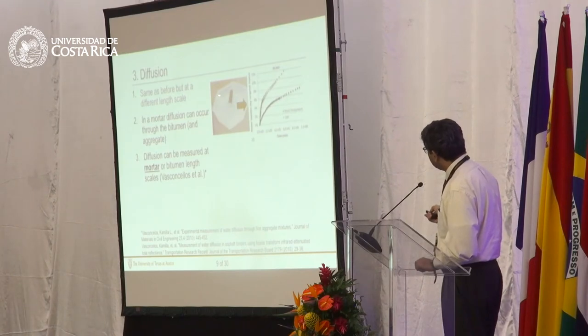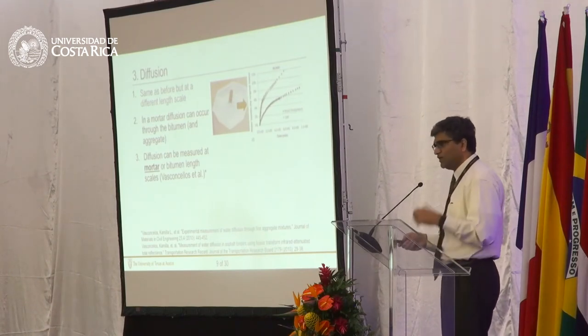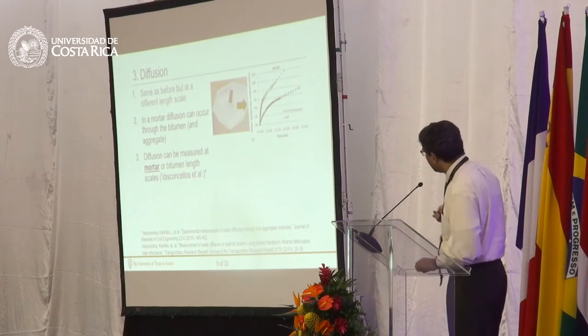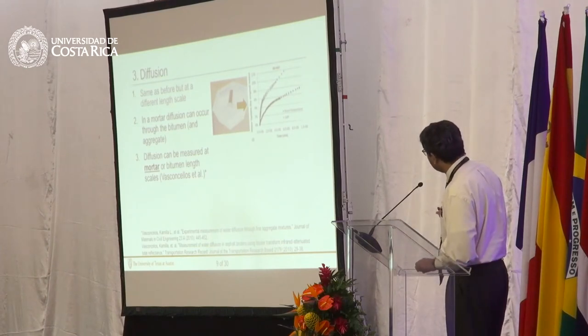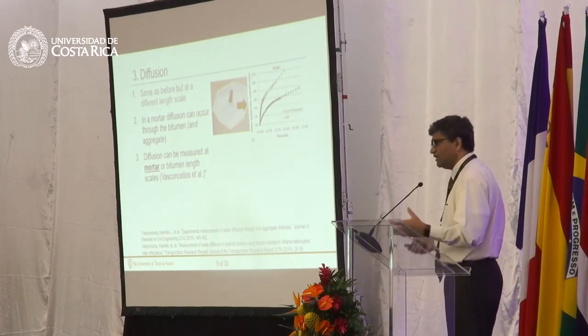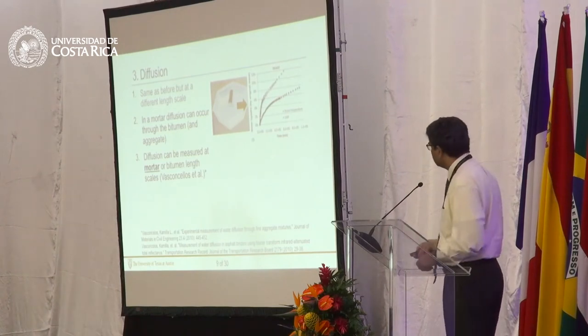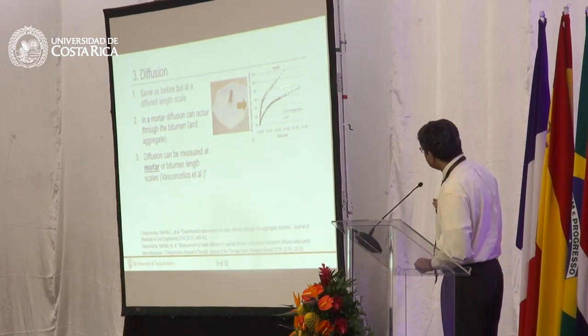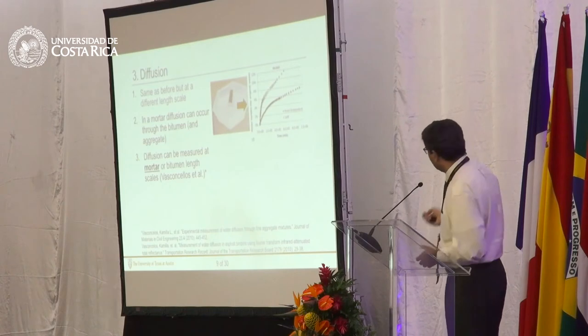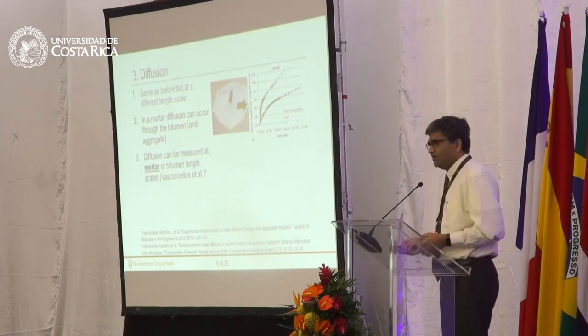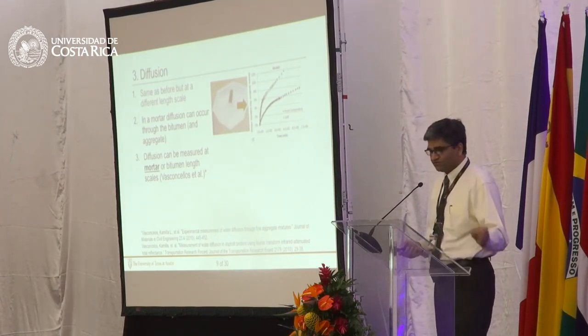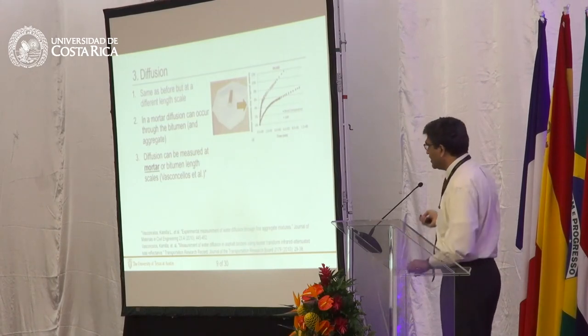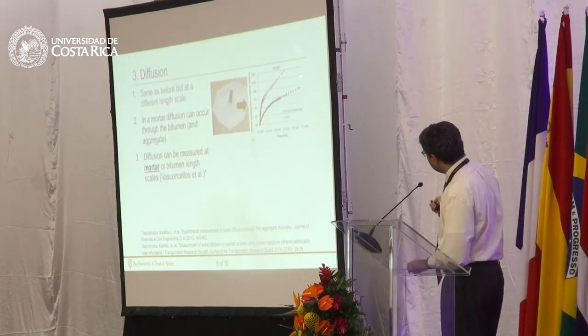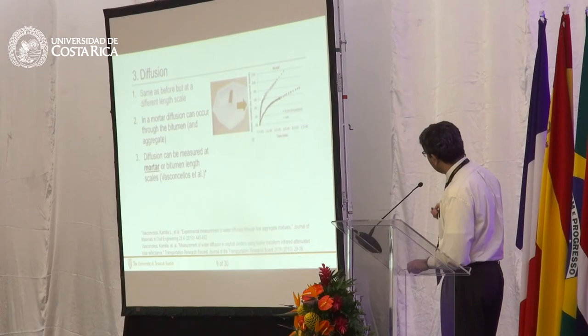What you would do is periodically take that specimen out and examine its weight, and you catalog the weight over the period of time. And what you see here is typical mass gain because water is diffusing into that specimen. So you have this kind of data that is collected from a very simple experiment. All you need for this is a nice balance. And of course, you need a lot of time because you have to go in and weigh it every so often.